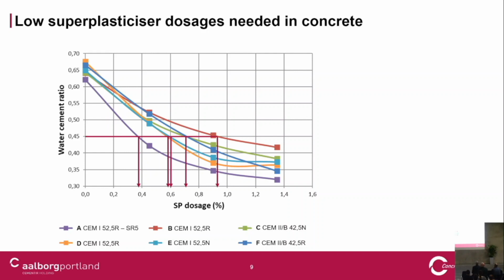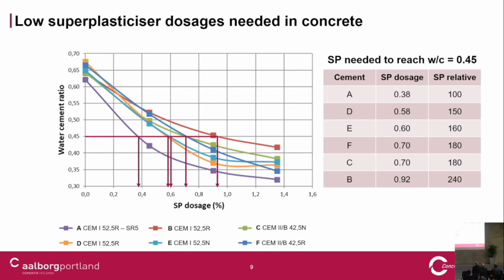For all the other cements, we need a higher amount of superplasticizer to obtain the same flow with the same water-cement ratio. So when we rank the cements, cement number A, that's our cement, needs 0.38% superplasticizer - you can say that's relative, that's 100%. But all the others need 150%, 160, 180, 180, and more than 2.5 times more superplasticizer to achieve the same flow. That is because of the unique clinker.